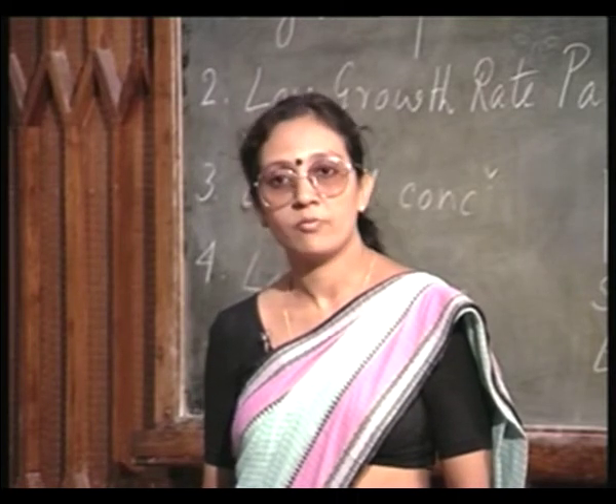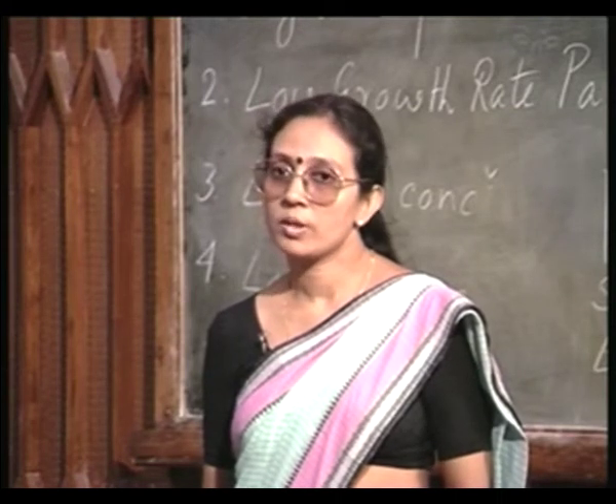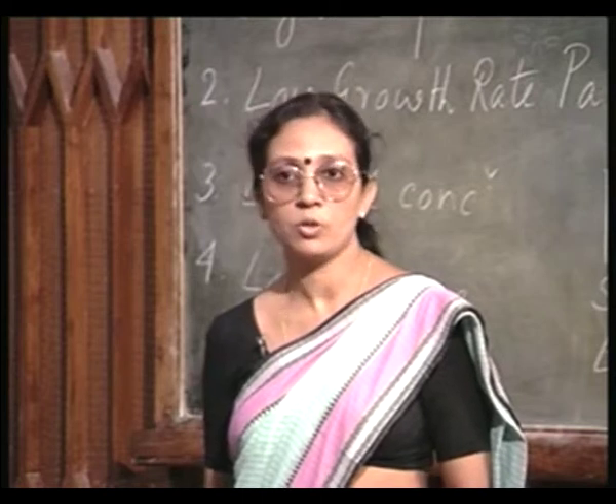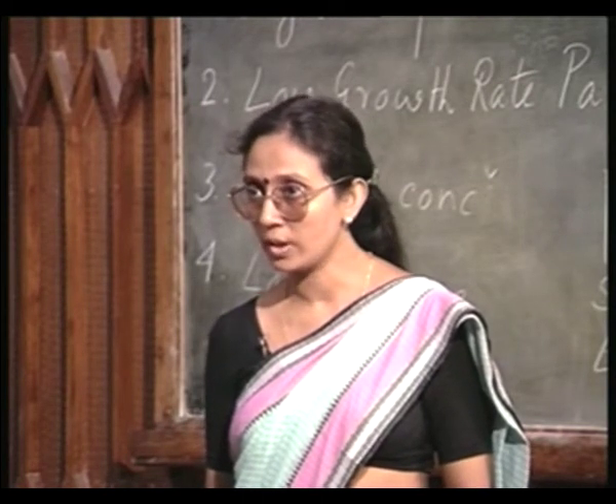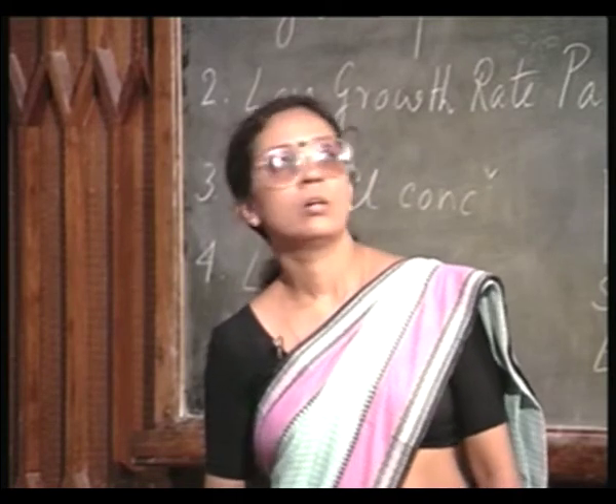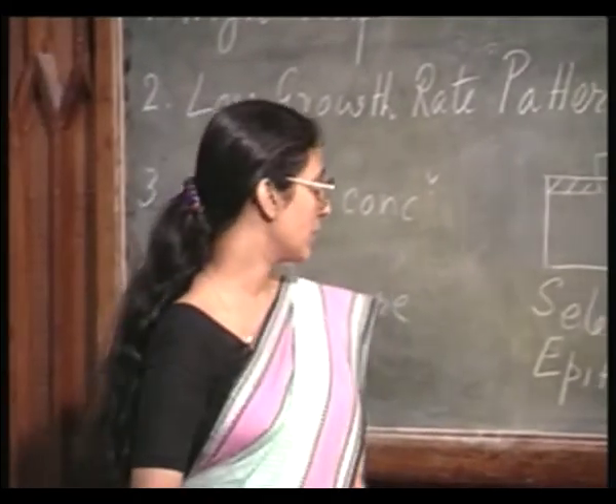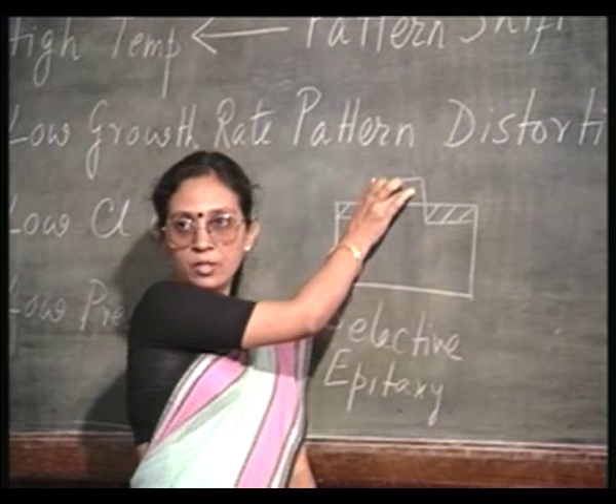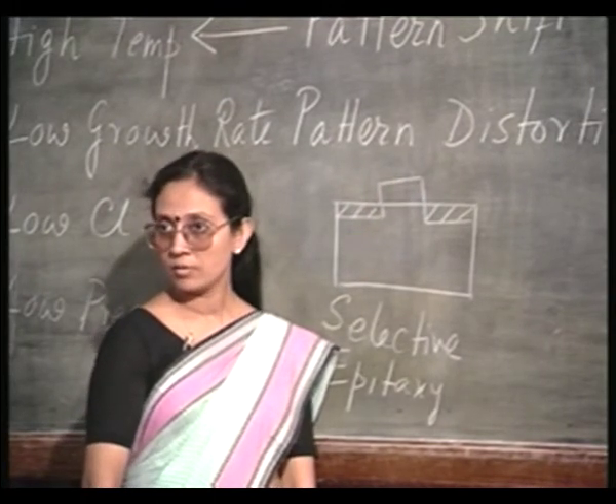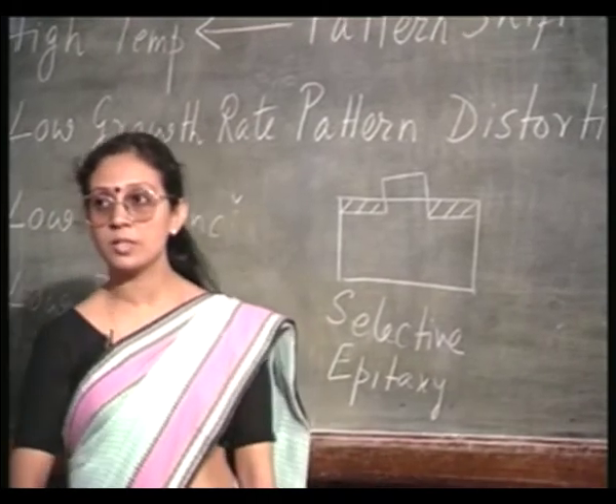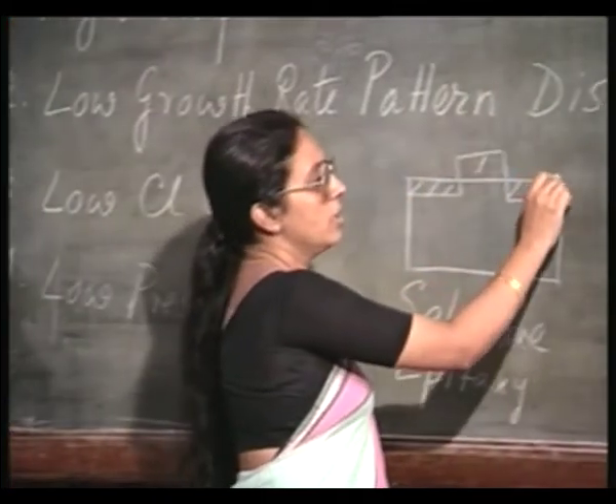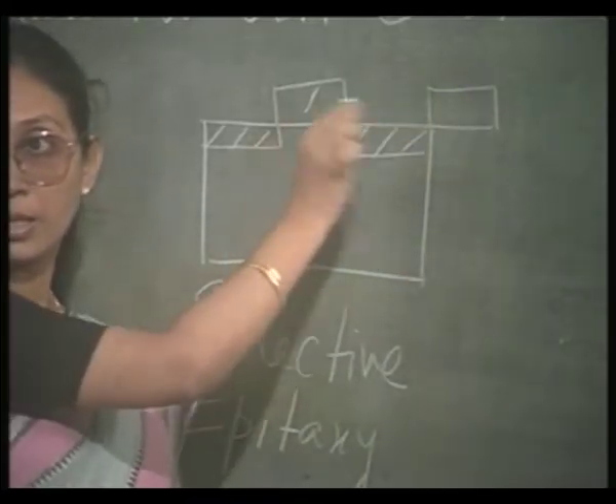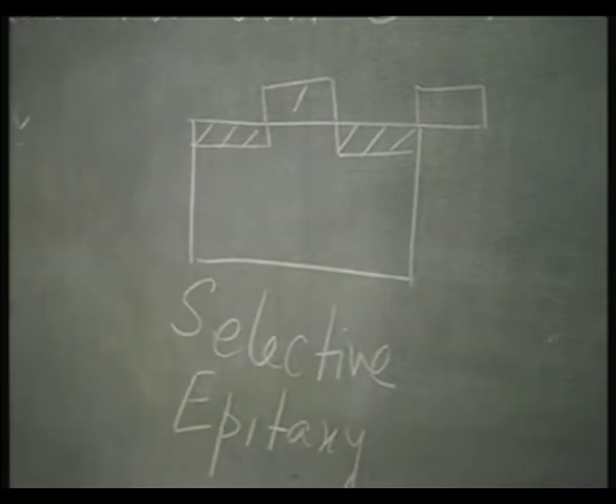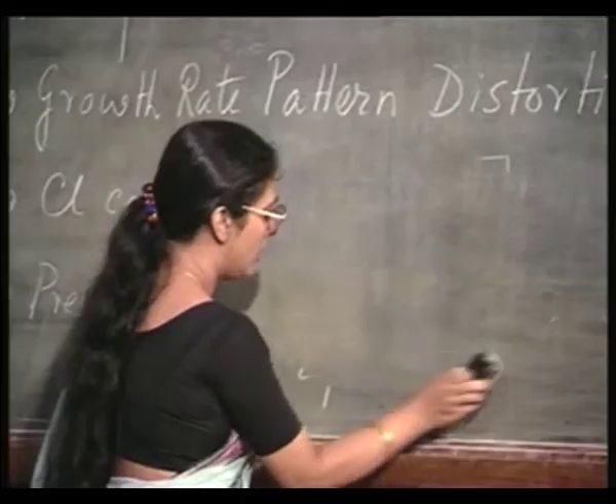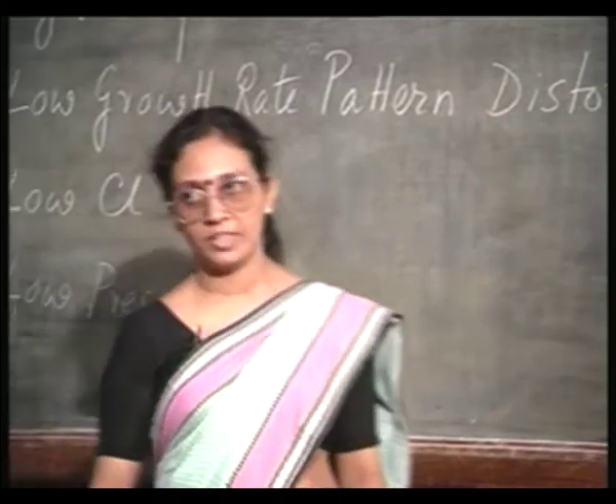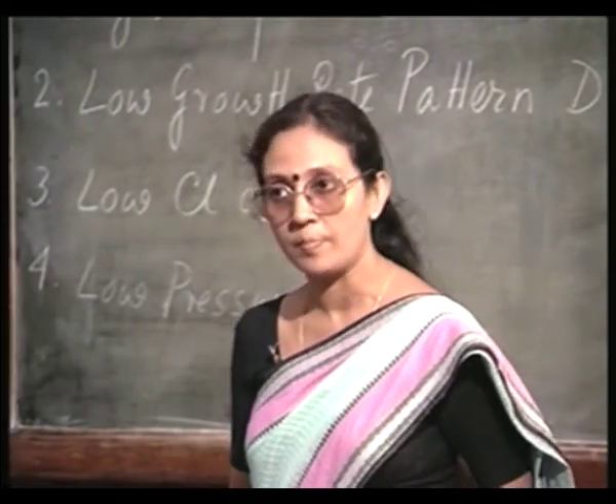Similarly, if you are covering it with polycrystalline silicon, then also it is quite simple to achieve, because on polycrystalline the growth will not be epitaxial, but it will tend to be amorphous or polycrystalline. So, selective epitaxy is quite an attractive technique, because you can have islands of silicon epitaxial region. So, the isolation between the devices is going to be quite simple. You have one transistor here, another transistor here, like that. They are automatically isolated. But in principle, they are all the same. They all come under the category of vapor phase epitaxy.